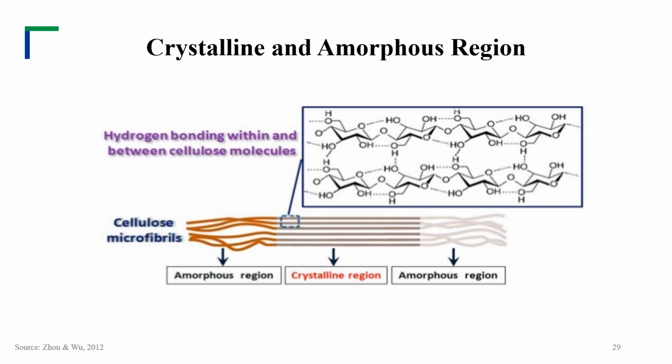One of the advantages of using a ball mill is that you can decrease the crystalline region of the cellulose. Cellulose has 2 different regions, which you can see in the slide. They're called the amorphous and the crystalline region. The crystalline region is well ordered, however, the amorphous is not organized well. The crystalline looks like uncooked spaghetti, where you can see the intermolecular bonding. However, amorphous looks like cooked spaghetti, and a large number of hydrogen bond sites